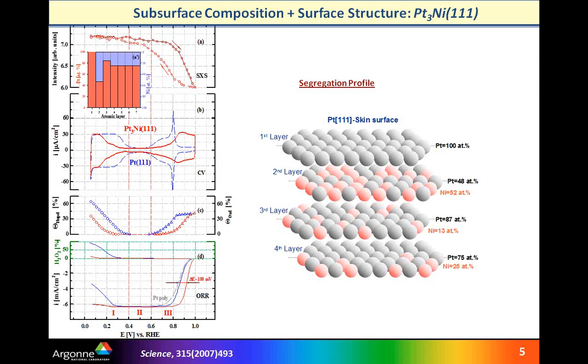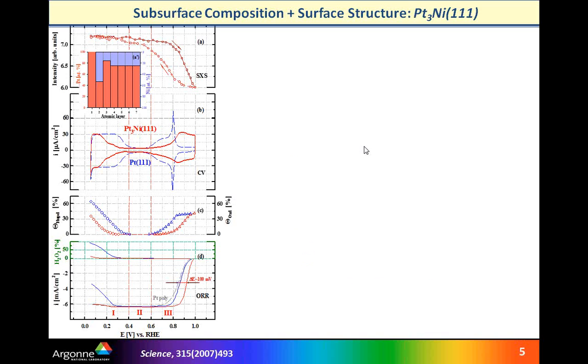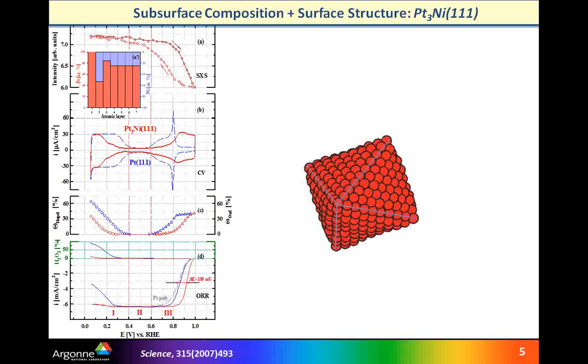This is in particular important for absorption of OH, because OH, which is formed in our case from water, not due to the dissociation of molecular oxygen, is absorbed on the surface, and this coverage by OH is controlling availability of platinum skin structure for dissociation of molecular oxygen.